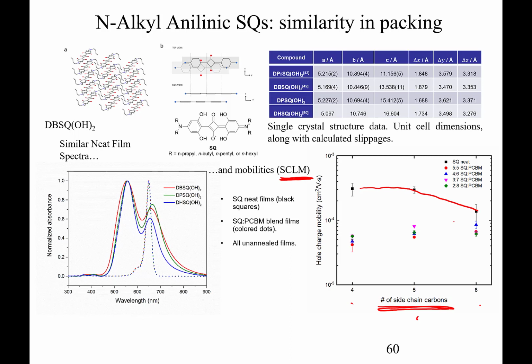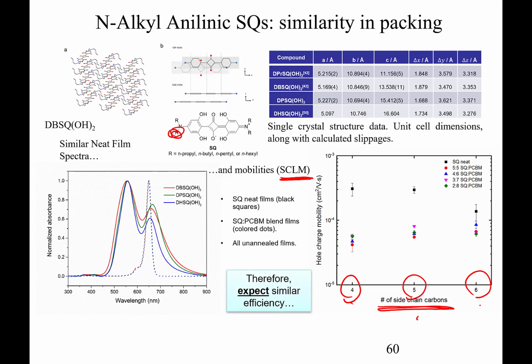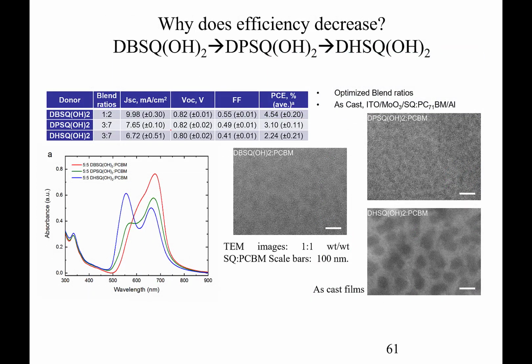It turns out that when we have these mixtures of the Squaraine with the PCBM, actually the mobility, the hole mobility starts to go up a little bit. But we'd pretty much say that there's really very little difference when it comes to mobilities between Squaraines with different side groups, whether it be 4 carbons, 5 carbons, or 6 carbons in that R group on the side there. So therefore we should expect similar efficiency. So what do we see? Well, it turns out that the efficiency actually goes down quite substantially from 4.5% in here all the way down